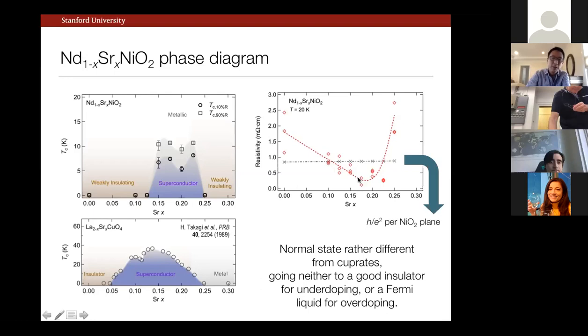And what's remarkable is that the superconducting dome occurs right here in this minimum of resistivity. Okay? And just to set a scale for what we're seeing in terms of this milliohm centimeter scale resistivity, this gray dashed line here is the resistivity you would get for a resistance quantum per NiO2 plane. So this is not to say that we know that it's so strongly two-dimensional. We don't actually right now have any direct experimental information on the c-axis conductivity.